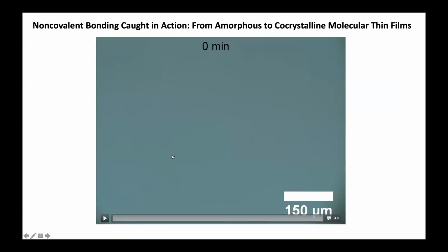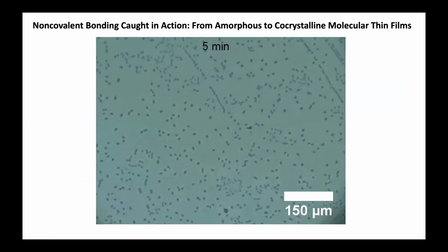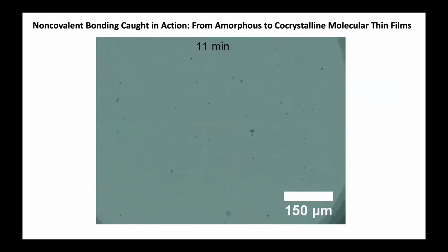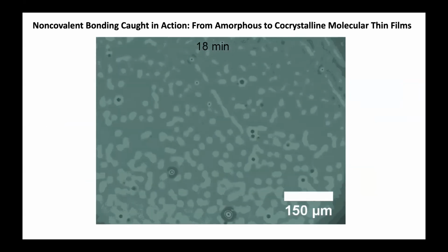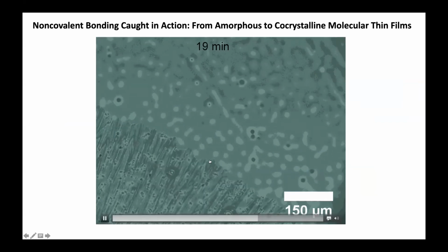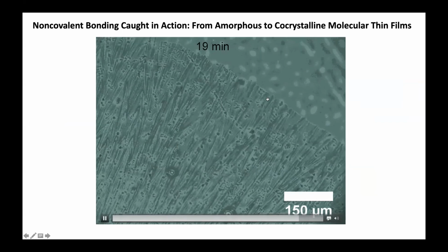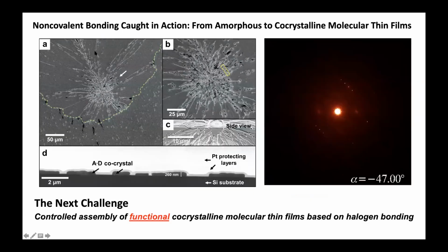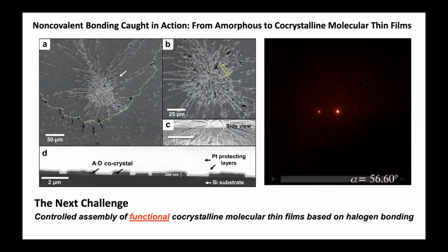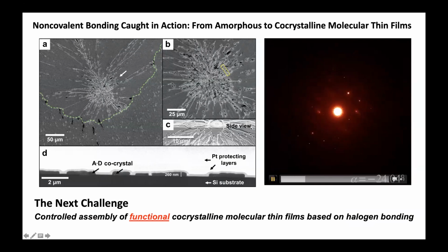If you look at the film surface of the first amorphous film that becomes crystalline, you see the following happening in time. This is at about 60 degrees Celsius, and at this moment you should see the spherulites appearing. The film starts to become actually co-crystalline. So you can also see the spherulites here, and you can cut those films and see a side view. When the amorphous film is continuous, when you look at the spherulites, you see here the material, here is a gap, here's the material, here's a gap. And we know that these films are crystalline from powder X-ray diffraction measurements, but also from micro-ED. You can see here nicely the diffraction patterns when we measure those films.